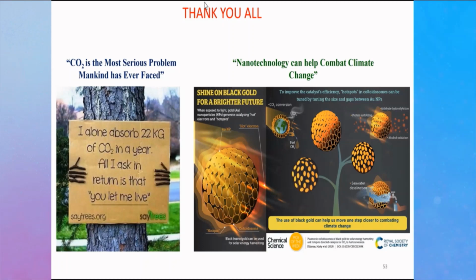Danish Babu Charge, tell about your opinion of using MOF as a catalyst for CO2 conversion. I'm not an expert in this field, but there was already a talk, and there's lots of interesting work going on where people are using MOFs for CO2 conversion. Obviously, the advantage of using inorganic material over organic material is the stability. You can see I can heat silica to 500 or 600 degrees Celsius. I cannot do that with a MOF, right? So the stability could be better when I use inorganic material over the organic MOFs.